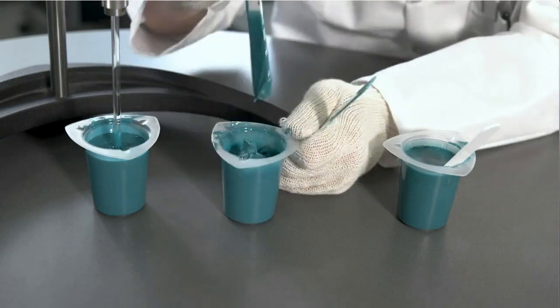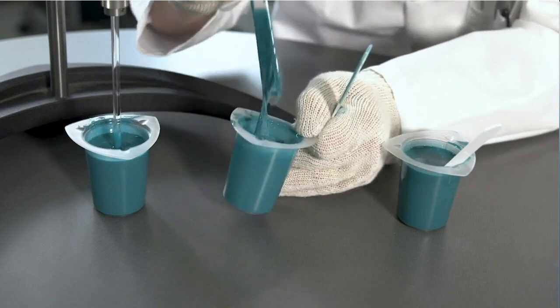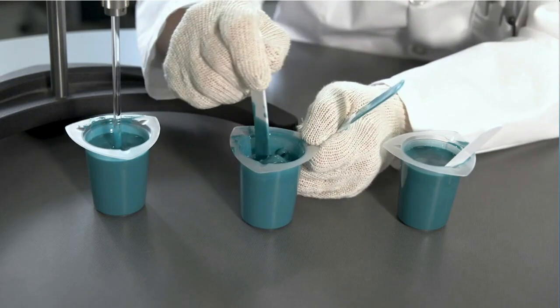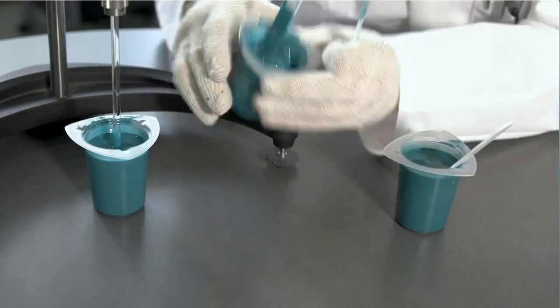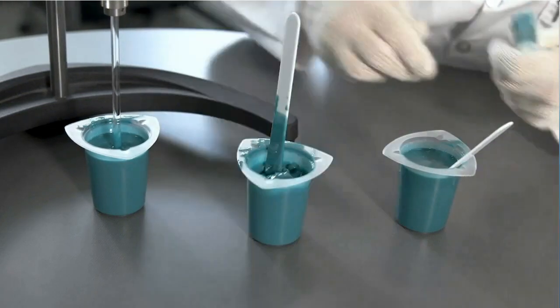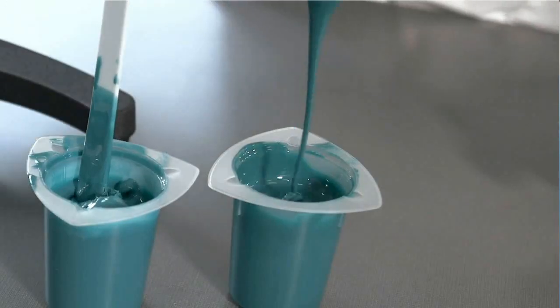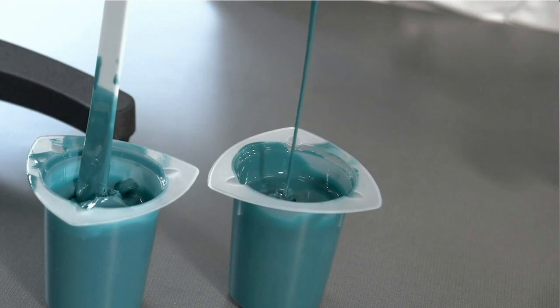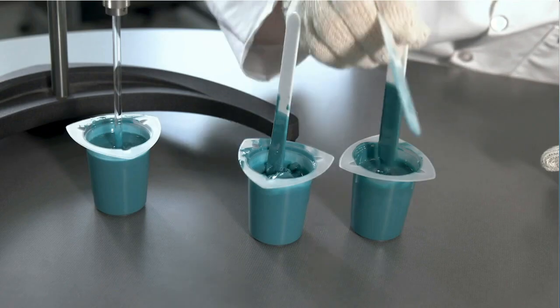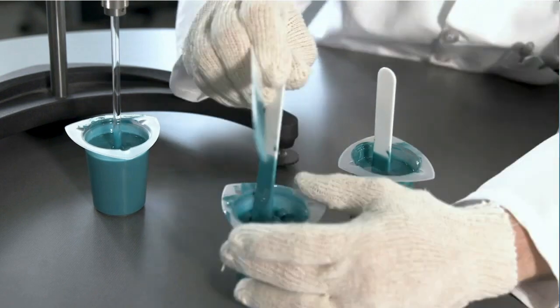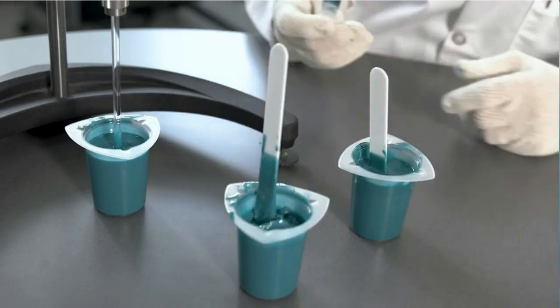It is distinctly gelled. Very distinctly solid in that center of that material, not flowing at all. Whereas this material would have more of a pot life. So this would have a much slower increase in viscosity. Obviously, this is a specific gel. This demonstrates the distinct difference between pot life and gel time of a thermoset polymer.